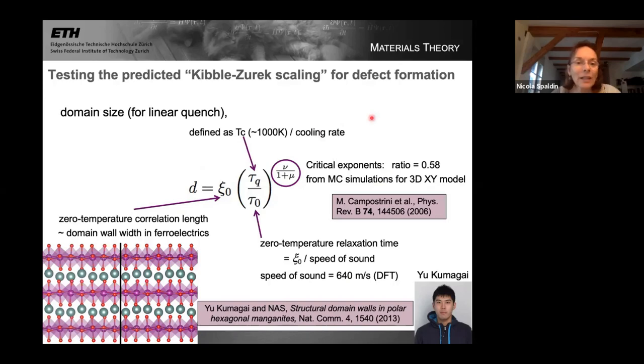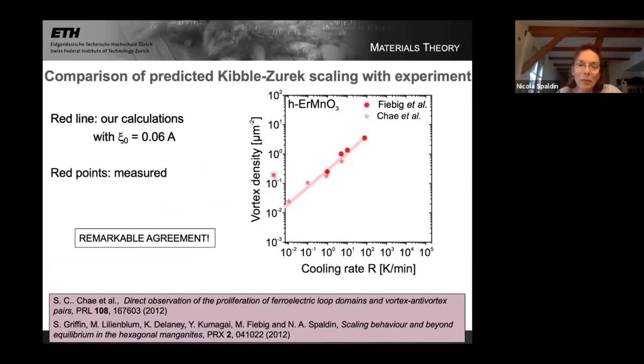So let me show you the answer then. This is a plot of the vortex density, the measured vortex density as a function of the cooling rate. The red dots are from the group of Manfred Fiebig, the data I showed you earlier, and the red stars are from the group of Sang-Wook Cheong. This is actually for erbium manganite, which is very similar to yttrium manganite, same structure. And the red line is the predicted Kibble-Zurek scaling. And the agreement is really remarkable. So the scaling is very much described by this Kibble-Zurek-like behavior.